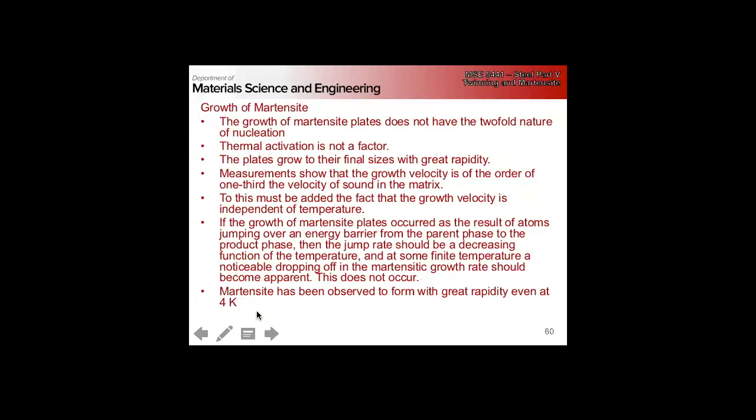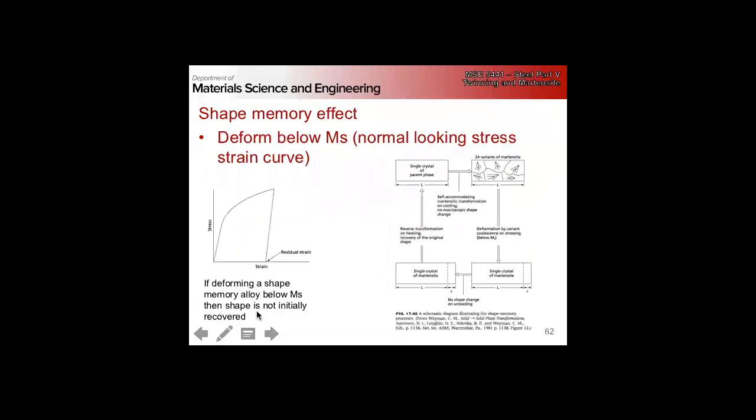And growth, we know it has to be largely athermal, and it happens very quickly, and the velocity doesn't appear to be diminished even at liquid helium temperatures, right? So it basically happens at the shear wave velocity of the material.